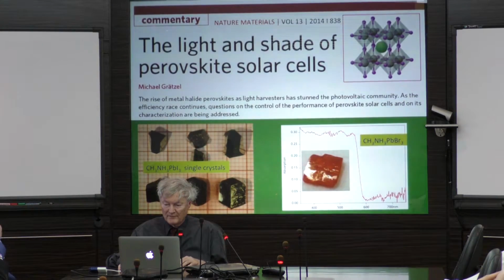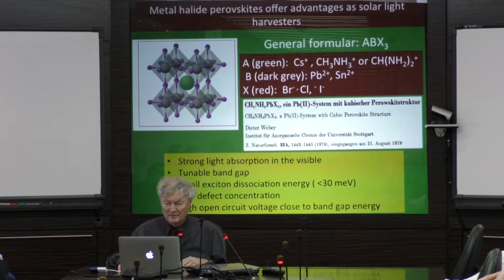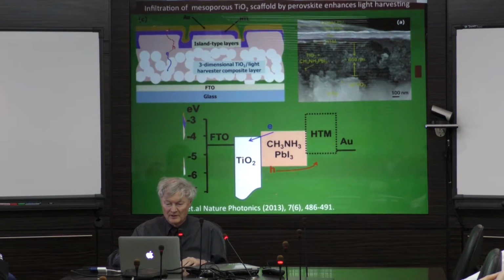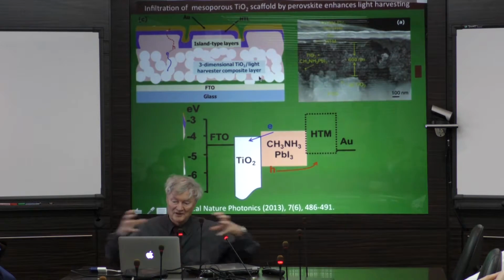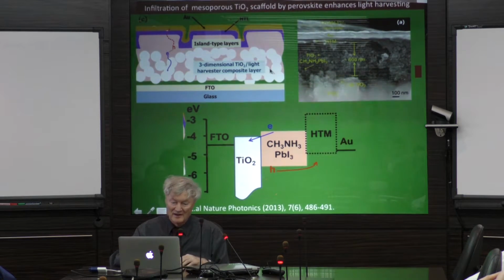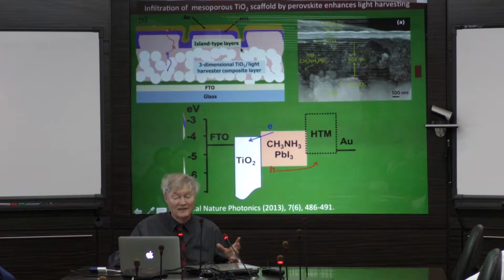And so they have very specific physical features. Let's not dwell on those. But what is important, it's really a very simple structure. You have the oxide scaffold, TiO2, the white particles. It's all printed. You print it on a support, the conductive glass. You infiltrate with a perovskite. You put the positive charge collector on top, and that's it.